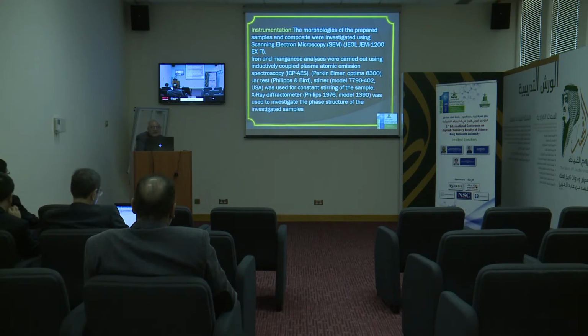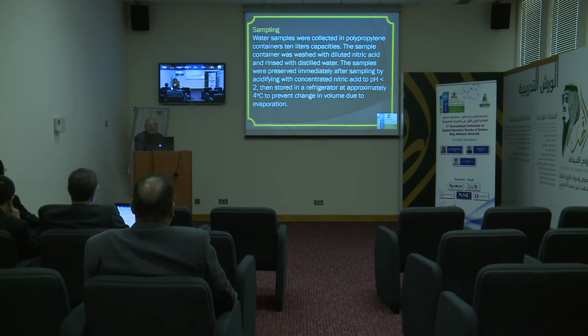Instrumentation: the morphology of the prepared samples and composite were investigated using scanning electron microscopes, and iron and manganese analyses were carried out using inductively coupled plasma atomic emission spectroscopy. Jar test stirrer was used for constant stirring of the sample. X-ray diffractometer was used to investigate the phase structure of the investigated samples.